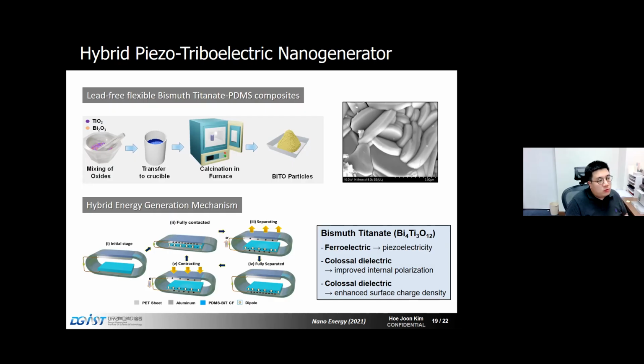So we used a high temperature calcination process to make this perovskite powder. It is bismuth titanate. It has a ferroelectric property, so it's piezoelectric. It is also a colossal dielectric, or very high dielectric constant or relative permittivity. So that property helps improve internal polarization and also enhances surface charge density, because surface charge is proportional to the relative permittivity.